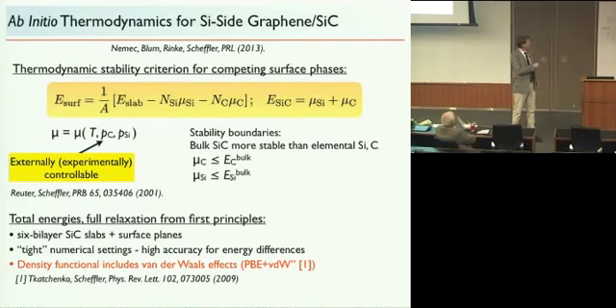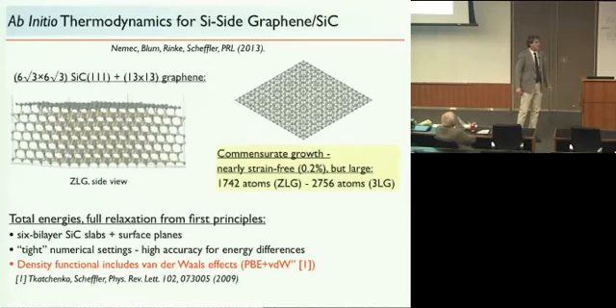We can do standard, in quotes, calculations in density functional theory here by so-called slab models made up of 6 bilayers and the surface phases. We can use high accuracy numerical settings and a density functional that includes van der Waals effects, which is important for the graphene in this case. But the key point is that these structures are large.